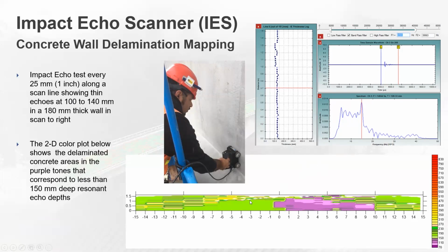And so this all got plotted up in a 2D color plot, which shows going from the normal expected thickness of around 180 millimeters, but a lot of delamination is present either on the near surface or the far side back of the wall. So it was able to map out very successfully where the damage was present in this 1.5 by 30 meter section of the wall. And scans were done here approximately every meter along the length of this wall. It was a 1 to 2 meter spacing on this. I think it was 1 meter in the center area and 2 meters left and right of center.